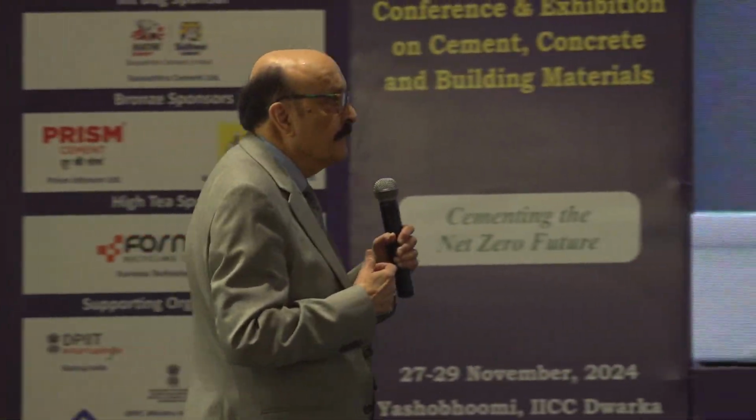With respect to the graphene reducing the crystalline size of calcium hydroxide. Oh yeah, that's a very good question, and I don't have the answer why addition of GO reduces the crystal size. One speculation is that, as I showed you, especially with graphene oxide, calcium ions are attached to the GO, and so maybe there is less calcium dissolution and lower calcium hydroxide crystal size, but I don't have a good answer. But we have seen with XRD that indeed calcium hydroxide size is different.